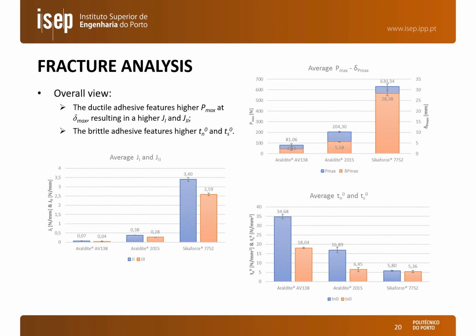Here we have an overall view of the results obtained, the average G1 and G2 for the three adhesives, the average maximum load and the maximum load displacement of the P-delta curves, and the average cohesive strengths in tension and shear. We can see that regarding the toughness, the Sika force is the best, while regarding the strengths, the brittle AV138 clearly has the higher strength between the three adhesives. And we can also see that we have some scatter, but the results are good.